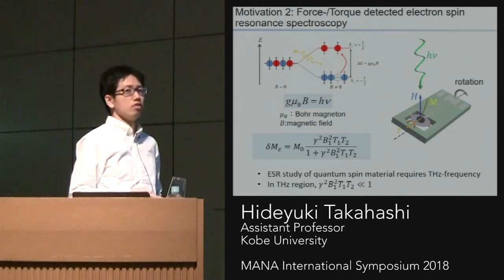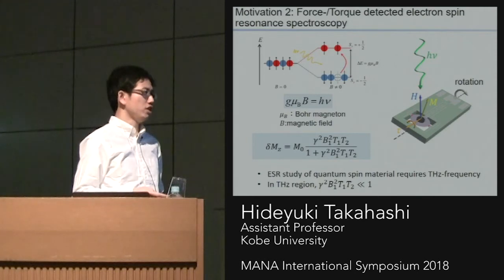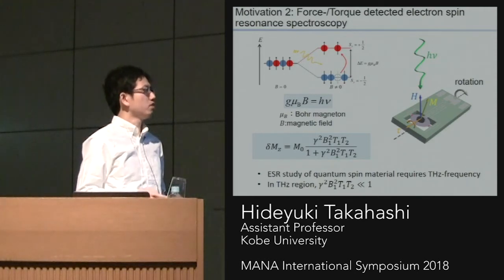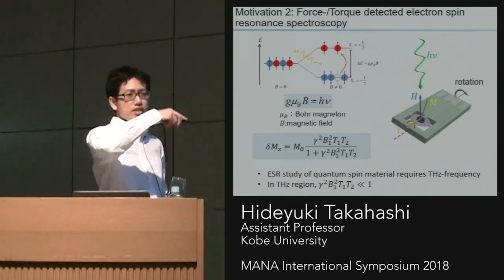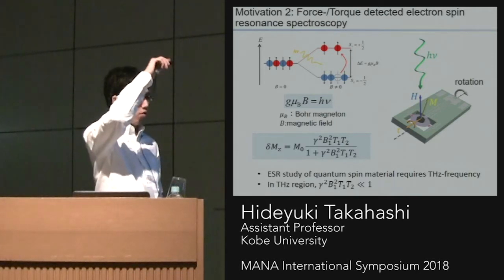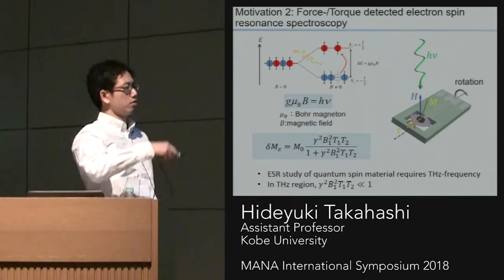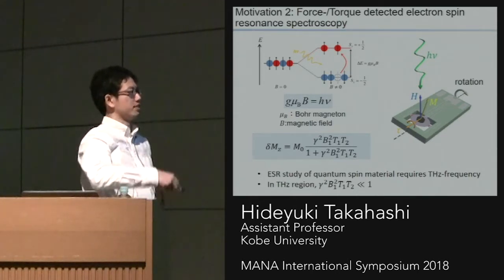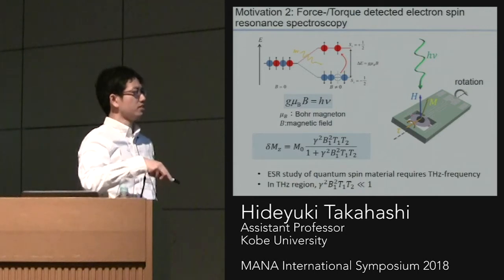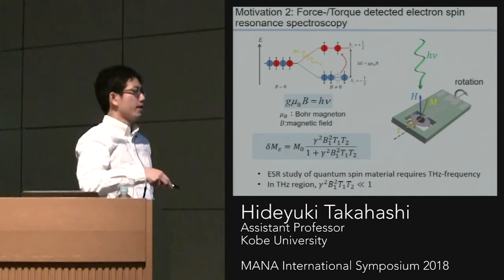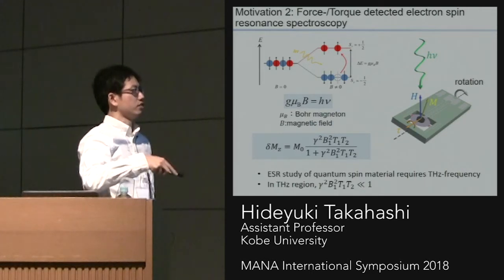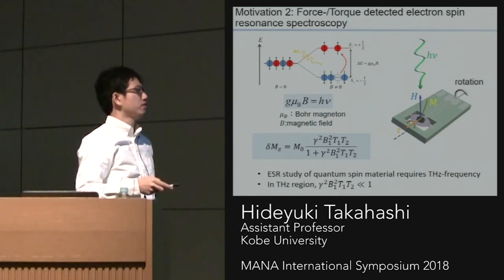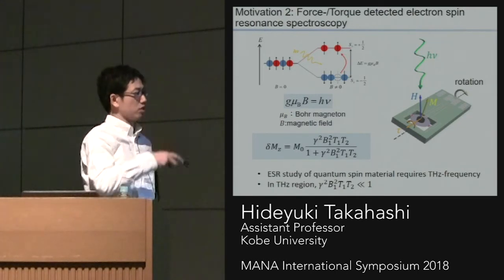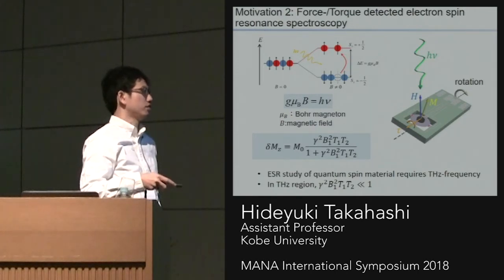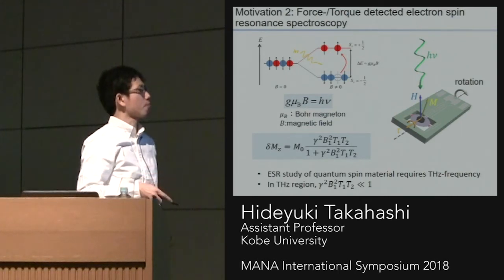In the ESR study of novel magnetic material, we need terahertz frequency. But we have a problem. As electromagnetic wave frequency increases, the power of the light source decreases. So it causes degradation of the sensitivity. So we need to enhance the detection sensitivity. For that purpose, we use a mechanical sensor, and this can achieve much higher sensitivity than the conventional method in this frequency range.